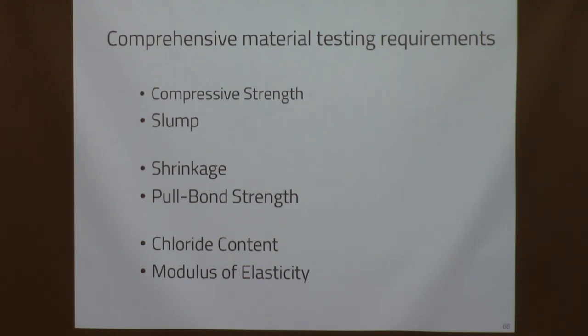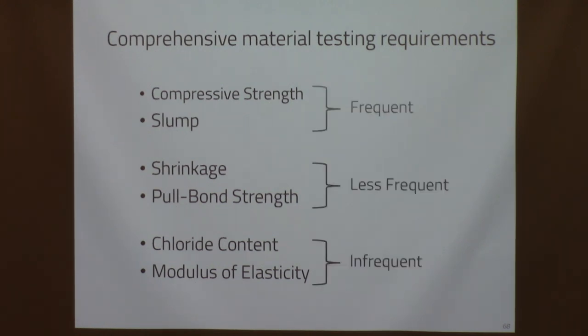Pull bond strength, that's the measure of, you know, what's the strength at that interface between the new concrete and the old concrete. And then obviously we didn't want to be adding chloride, so due diligence would say make sure we don't have any added chloride to it. And then modulus of elasticity, again, isn't a big one, but one of the things that you learn in concrete repair is that you really want the new concrete to be very compatible mechanically to the existing concrete. You don't want to have this super high concrete with a high modulus next to something that's just your basic 4,000 PSI average modulus of elasticity. So we ran some modulus tests just to confirm that we didn't have some, you know, super high strength concrete.